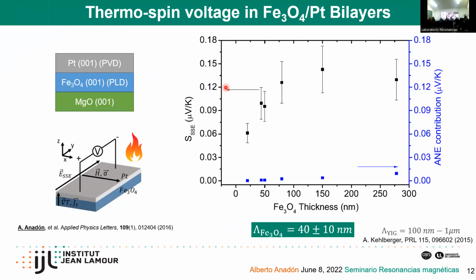So basically here, what we did was change the thickness of this magnetite film from a few nanometers up to almost 300 nanometers. And we studied how the spin current generation was in the system. So to do this, what we did was measure the spin-Seebeck effect. We applied a thermal gradient in the out-of-plane direction using a resistive heater. And by putting two contacts to measure the thermal voltage and sweeping the magnetic field, one can see how this voltage increases as the power applied to the system increases.